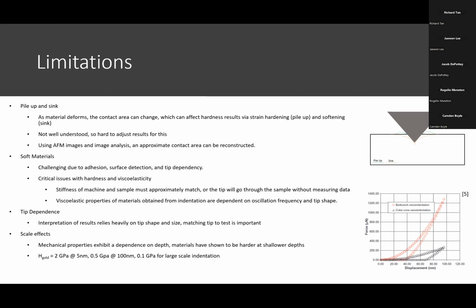If you look at the top right figure, you get an example of pileup - that's the material moving out of the way and pressing more against the tip, which gives you a higher contact area. Then sink, as it moves away when you indent, gives you a lower contact area. Both would adjust how you calculate your hardness, Young's modulus, and other mechanical properties.